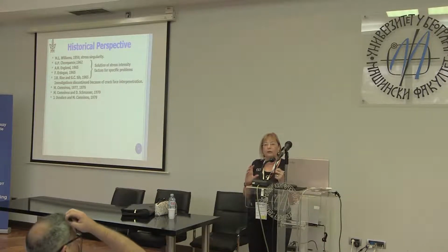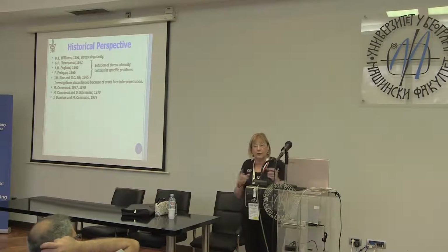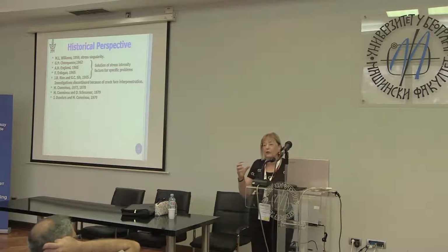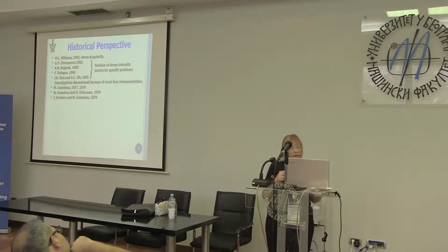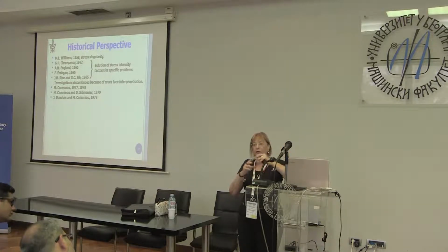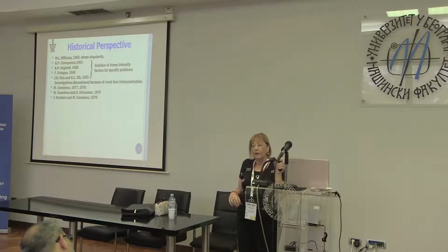And it depends on the value of epsilon whether it's 10 to the minus 4 or 10 to the minus 10. Well, if it's 10 to the minus 4 times the half crack length, that's fine. I mean, who cares? It's certainly within any sort of nonlinear small-scale zone that you could possibly have. But then she goes on in the next paper in 1978 to look at a crack where the body is in shear. The same body, two materials, a finite length crack. And at one side, she finds basically the same thing as for tensile loading, but on the other side, she finds that the contact zone, it's not overlap, the contact zone is about a third of the half crack length. So that's serious, but at least she's quantified it for us and she's given us a hint.